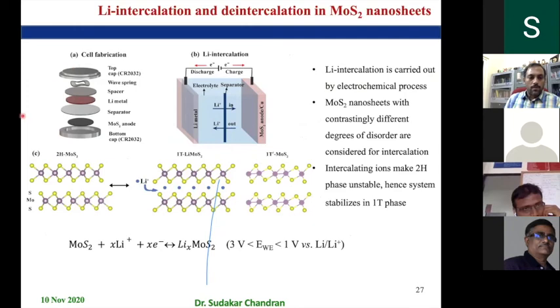Yeah, so the X is 1. LiMoS2. Of course, if you try to push too many lithium, the moly disulfide is not stable. Li2S will come out and moly will get thrown out. So it becomes a two-phase scenario. From that onwards, it's kind of a lithium sulfide battery. So Li and Li2S is the reactive agent.